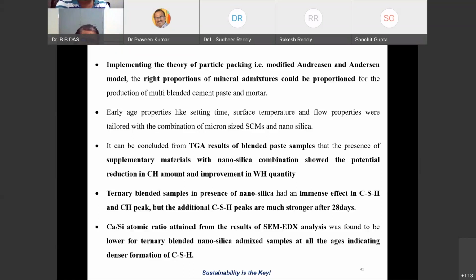From the TGA, the presence of supplementary cementitious materials in combination with nanosilica showed a potential reduction in the calcium hydroxide amount and an improvement in the CSH quantity. Well, alone it is fine, but if you are adding a small percentage of nanoparticles or some microparticles, that is changing the dimension of the hydration behavior, changing the dimension in the microstructure characteristics.